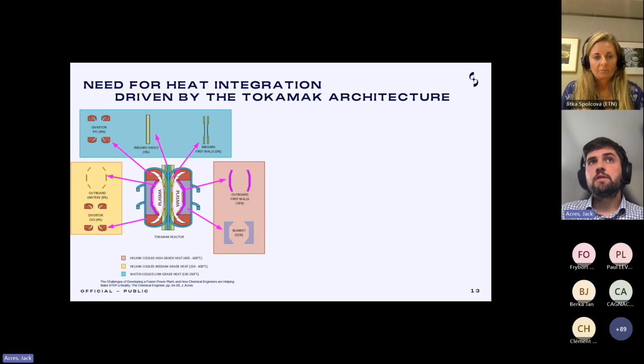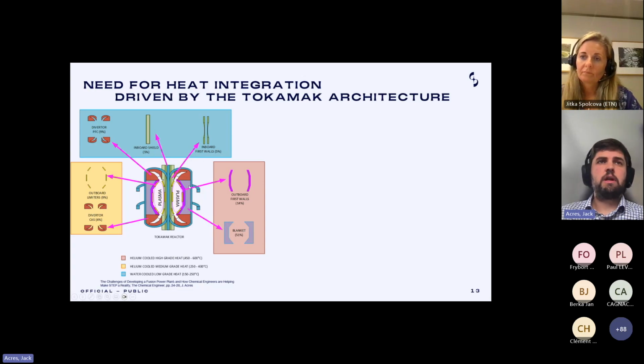Now let's talk about heat integration. So the tokamak is not just one machine. Unfortunately, it's made of many different components, which all have very special heating or cooling requirements, I should say. So for example, our blanket is where all of our tritium breeding happens, and there's a volumetric heat load, which therefore means we can get quite a high temperature out of it, whilst our divertor we'll see is effectively what we call the ashtray of the tokamak, and we'll see very intense heat loads as the plasma comes through here, and that will see very, very large surface heat loads, which must be cooled at relatively low temperatures. So we can't get good grade heat out of this.